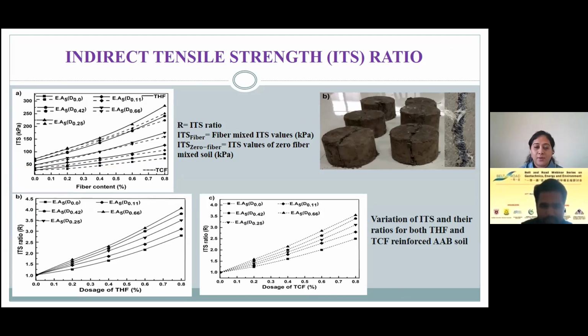That's a very nice question, actually. The major challenge which can be faced is the evolution of heat. When we actually go for mixing the fly ash and slag with this activator solution, there is quite a large amount of heat which is evolved. So that is why when we have mixed this fly ash and slag with this alkali activator solution, we have kept wet jute bags so that the geopolymerization reaction can be over, and the heat of the geopolymerization reaction can dissipate. So that can be one of the major challenges in the field.